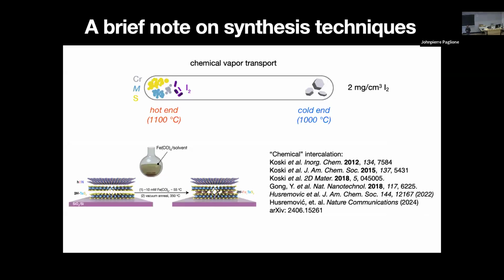And so thinking about synthesis, I've used the term intercalation, and they are intercalation compounds because there's a host lattice and then there are these intercalants. But most of the time when myself and others grow these crystals, we grow them as we would any other bulk 3-dimensional material. It's not as if we create the host lattice first and then necessarily perform some other intercalation, though that's what I'm showing in the bottom here. Most of the time, these materials are synthesized as bulk crystals by chemical vapor transport, right?